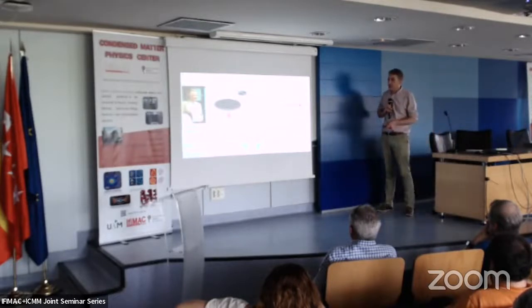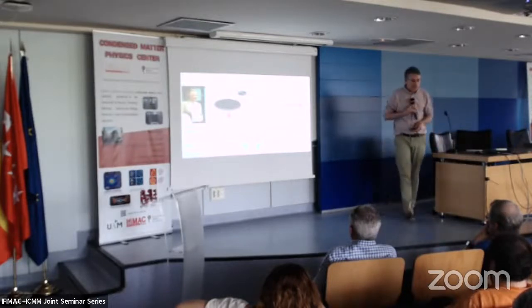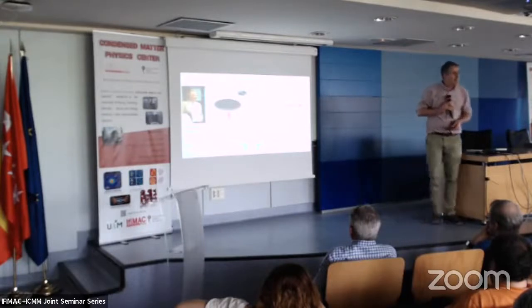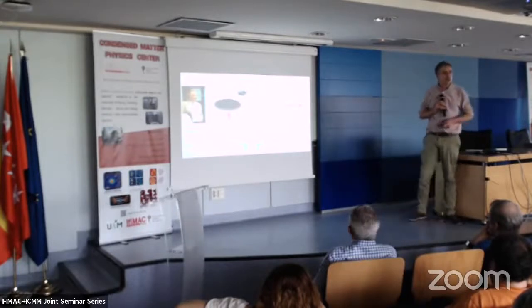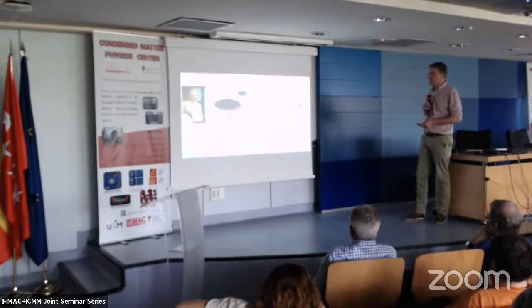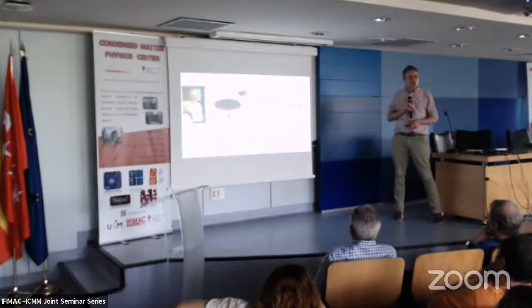And Andreev took up this challenge, and he proposed one new phenomenon which happens in superconductivity. He realized that if you approach with an electron into something close to a superconductor, the gap slowly opens, and the electron slowly transforms into a hole because of the change in the dispersion relation. Then the hole is exactly retroreflected, and the Cooper pair falls into the superconductor.